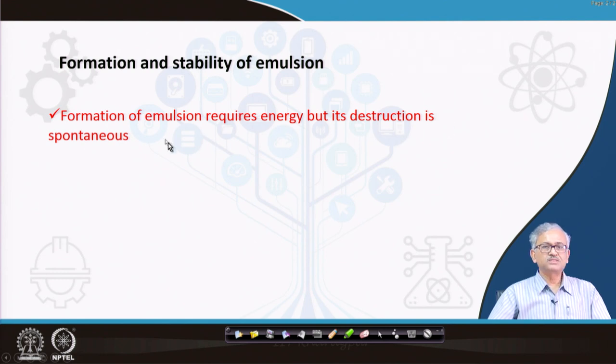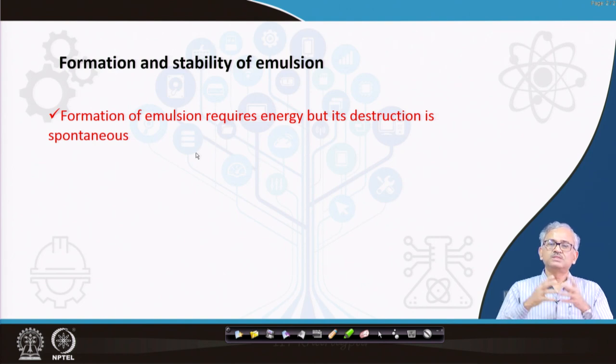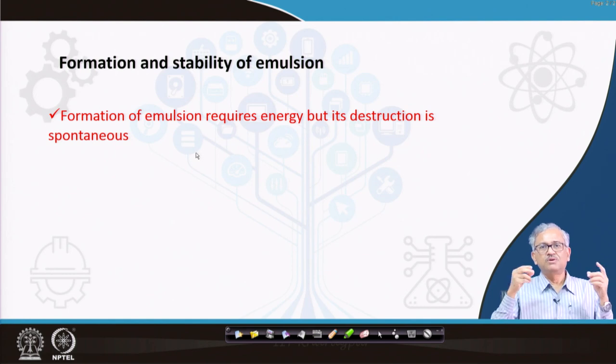But its destruction is spontaneous. You form an emulsion, but the collapsing of the emulsion is a spontaneous process. Why is it spontaneous? Because in the emulsion you have created a lot of surface area, since all the liquid droplets and gas bubbles are there, small droplets with a lot of surface area. So you have a large surface area in the emulsion,